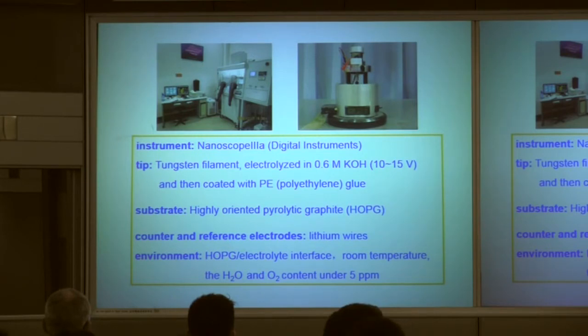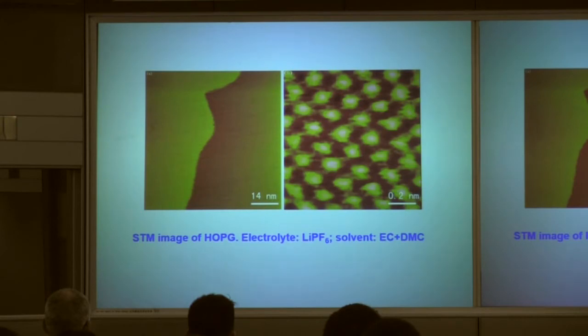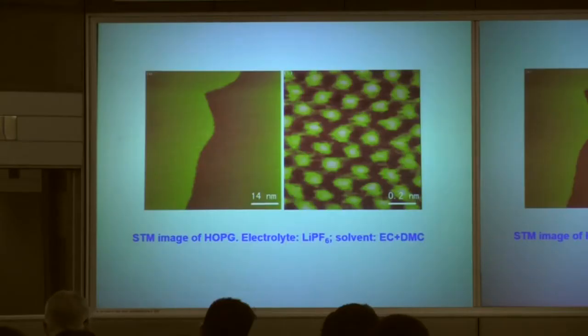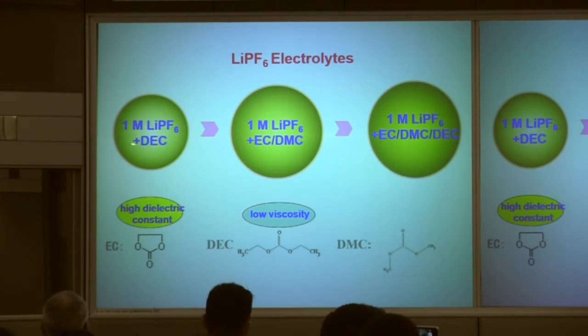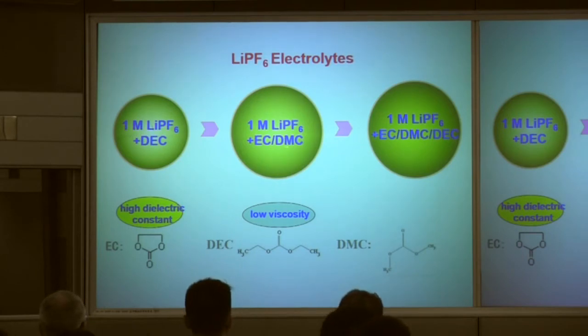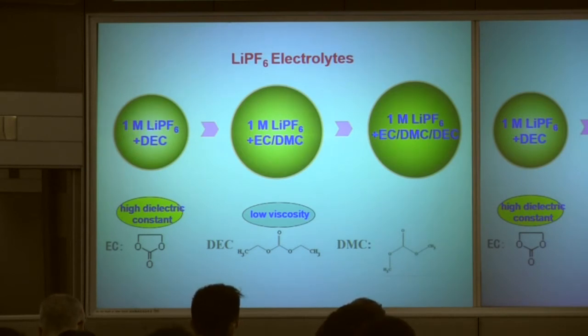Here are all the experiment conditions and results. At the open-circuit potential region — meaning no electrochemical reaction — the graphite surface is very beautiful, showing a large flat area with step lines and atomic resolution images of carbon atoms on the surface. We also put different additives into the supporting electrolyte: DEC, EC-DMC, and EC-DMC with DEC, since all these additives play different roles.